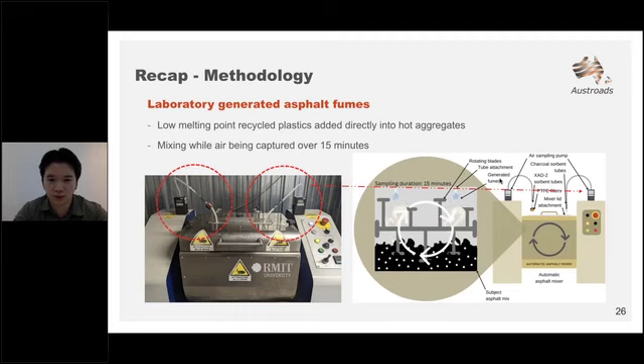All asphalt blends were produced over a mixing period of 15 minutes, during which the air is captured throughout the entire process via these pumps. The measurement for PAHs and VOCs uses XAD-2 tubes and PTFE laminated membrane filters and charcoal sorbent tubes for VOCs.